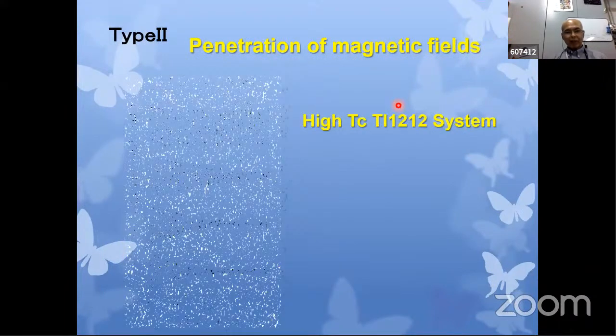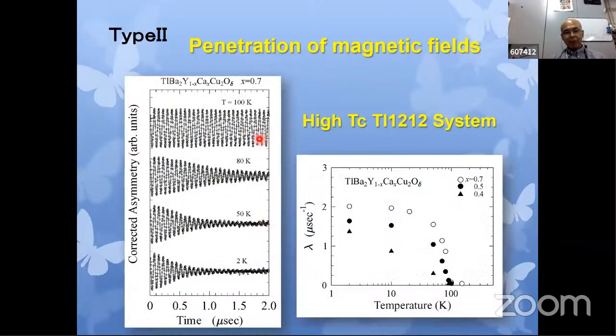On the other hand, this one is my old data. This is also high Tc data, in the normal state. We can see very nice muon spin precession like that. But in the superconducting state, the muon spin precession motion shows large damping, just like a muon spin relaxation property appears. And this damping becomes stronger with decreasing temperature. So this difference is caused by the superconducting state. Then the damping rate becomes higher, and becomes like this. This temperature dependence is also very important to discuss the superconducting state, because it corresponds completely to the density of the Cooper pairs.